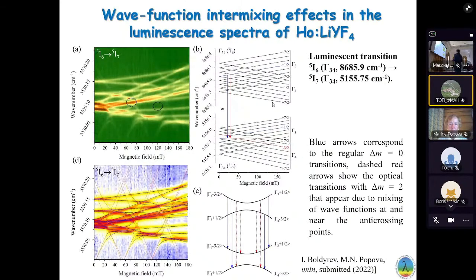The next thing, we observe a very interesting shape of the luminescence spectra in the magnetic field. You see, we named it like bugs or some structure with wings. And the first time we looked at this picture, we didn't understand what the matter was. But when we calculated the spectra with wave function intermixing effects, you see we have a really, really good explanation of such structures. This work will be published in Journal of Luminescence.